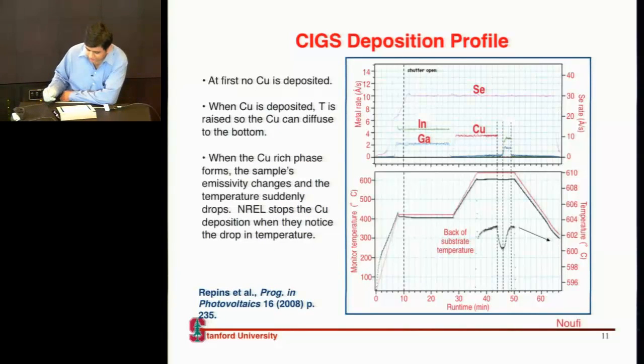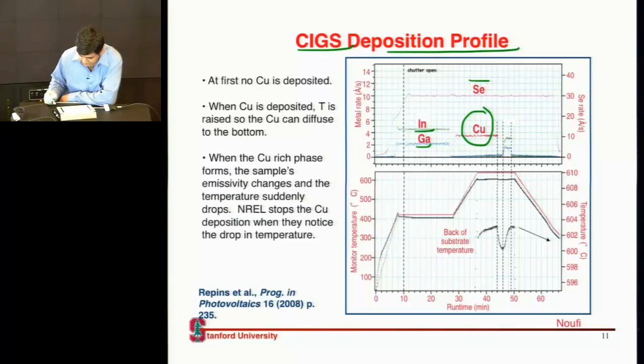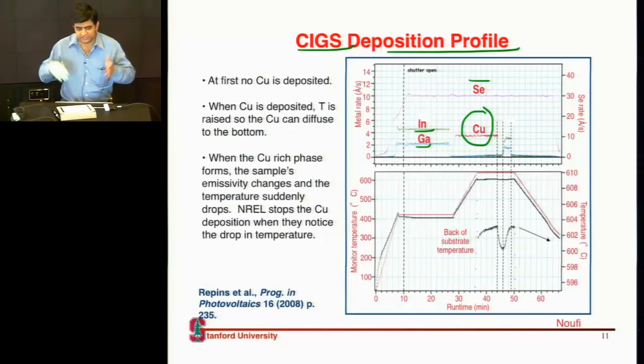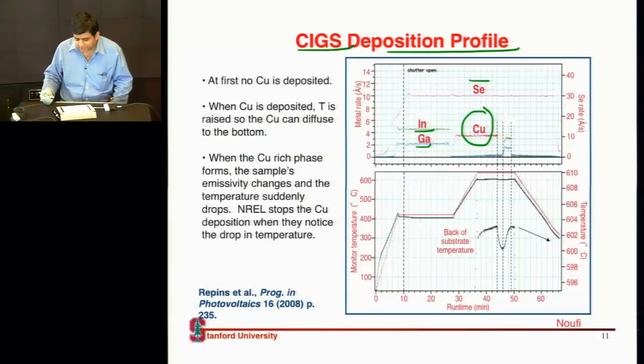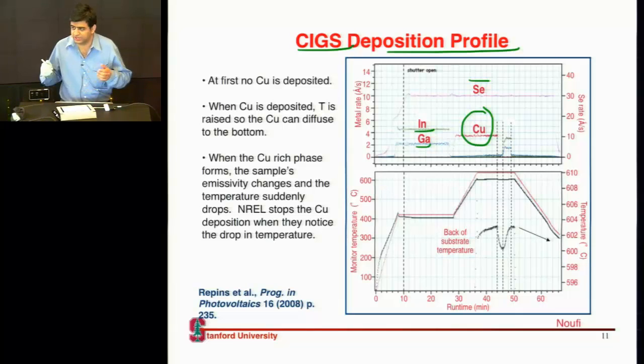One way of doing it: you can sputter indium, gallium, and selenium at the same time. Copper has different sputtering conditions compared to the other three, so you stop sputtering indium and gallium and then sputter your copper. Then you anneal it. The assumption is that these elements have high diffusability within each other, so they diffuse easily until they form the CIGS layer. You can't sputter all four at the same time because they have very different evaporation conditions, so you sputter at most two or three, then the other one, and then mix them together.